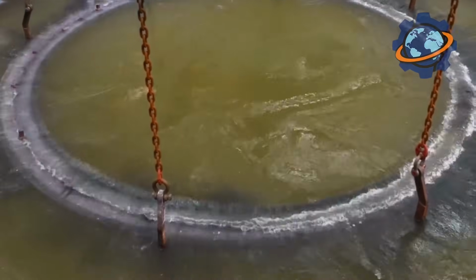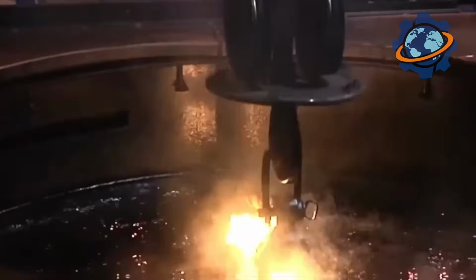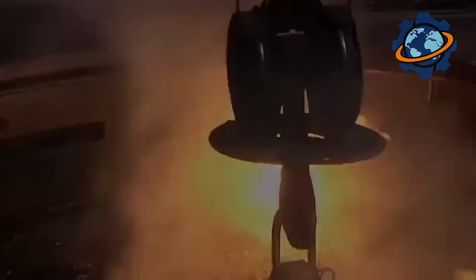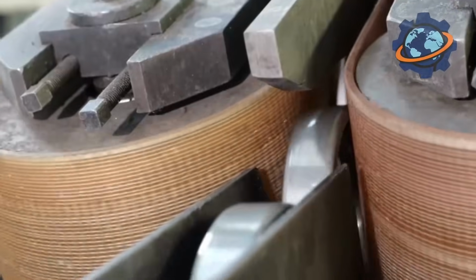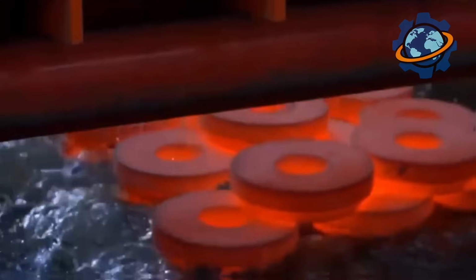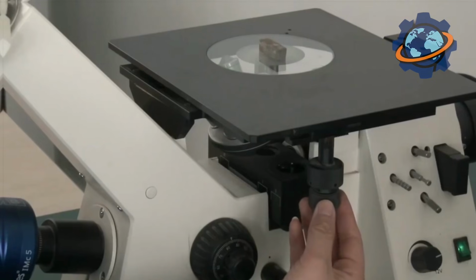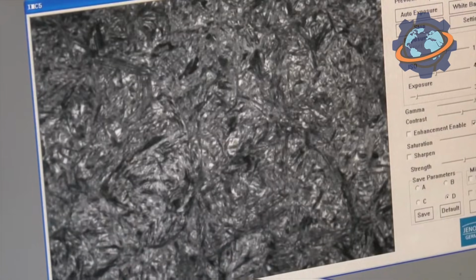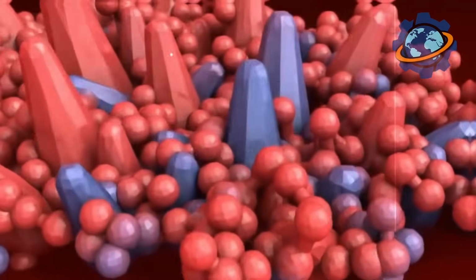Then comes quenching, the most dramatic moment in a bearing's life. The red-hot ring gets rapidly cooled by plunging it into an oil bath. The temp drops from 1600 to 300 degrees Fahrenheit in a matter of minutes. The oil hisses, boils, creating clouds of vapor. This sharp temperature shock transforms the steel's internal structure into martensite, a super hard crystalline form.